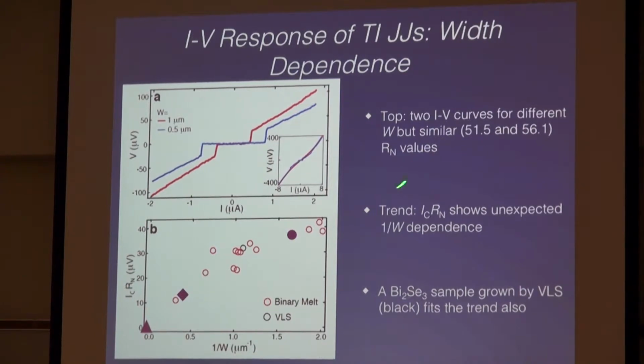This is the current you apply to the device, and this is the voltage that you measure. And you can see for small values of current that you apply, no voltage develops. And at some point, you hit a value of current that the voltage jumps up and moves linearly away from that point. This is a very typical behavior for a Josephson junction.